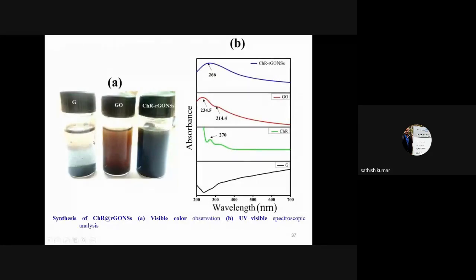For a clear understanding, I will explain more clearly. In the pristine graphite, we have the carbon-carbon backbone. After the oxidation, some oxygen functional groups are present in the graphene oxide. These two absorption peaks indicate the presence of the oxygen functional groups due to the oxidation process.